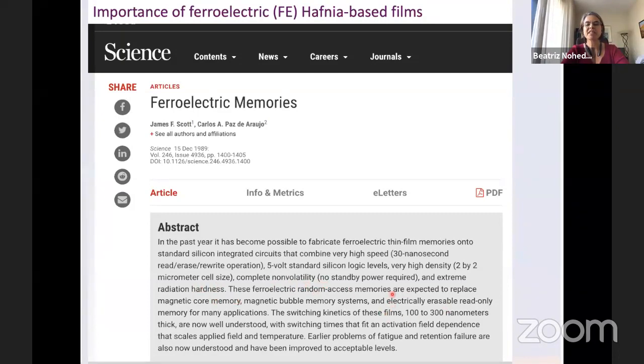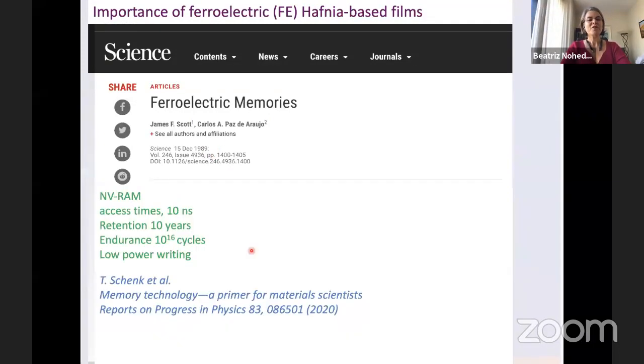And at that time they were talking about films that were lead containing or bismuth containing and were like 100 to 300 nanometers thick. And remember, it was 1989. So indeed, ferroelectric memories are very interesting because they are non-volatile RAM memories. They have very short access times, very long retention, and nowadays very good endurance, like 10 to the 16 cycles, with very low power writing needed.